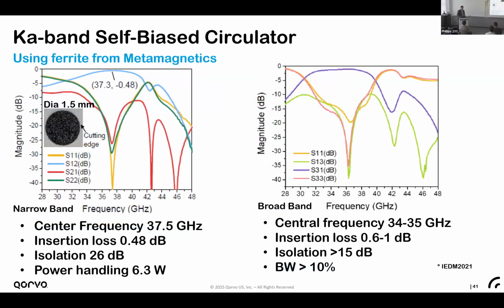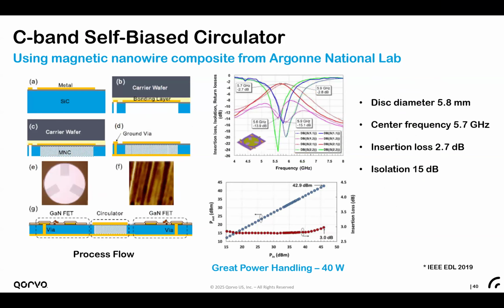And for C-band, before we move on, this is Jim Huang. I think the isolation of 15 dB may not be enough. Yes, I agree with you. You're right. That's why we are looking at optimizing the material itself and see how we can further improve it for the C-band application. And sometimes it also depends on the design. We had some difficulty getting very good consistency of the material from batch to batch. That's also why having it in a production mode is very important, to have a consistent material supply. But yes, I agree with you. Our target is to get at least 20 dB isolation with these devices.